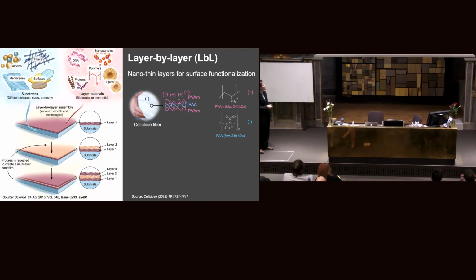PAA, polyacrylic acid, is a negative anionic polyelectrolyte. They can be assembled layer by layer on the surface of cellulose fiber. The whole process is water-based, with no toxic compounds involved, and at room temperature.